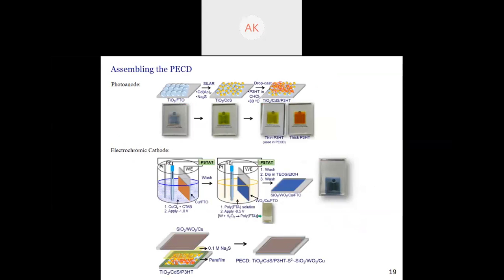Now, I have assembled my film. I have made a very thin TiO2 over FTO. I have deposited CdS via SILAR on the TiO2 and then drop-cast P3HT in chloroform at 80 degrees. Why I have this IITH logo throughout is that I want to show that this film never loses its transparency. Even if you have a thin P3HT layer, it is still transparent. The thick P3HT didn't work well for us, but I've just shown it to show you the color, how it is.